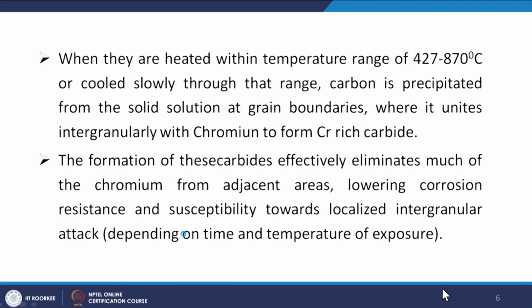Okay, when they are heated within the temperature range of 427 to 870 degrees centigrade and cooled slowly through that range, carbon is precipitated from the solid solution at the grain boundaries, where it unites intergranularly with chromium to form chromium rich carbides. Okay. The formation of those carbides effectively eliminates much of the chromium from adjacent areas, lowering the corrosion resistance and increasing susceptibility towards localized intergranular attack.